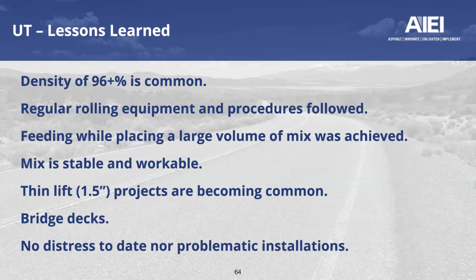What have we learned in the state of Utah? Well, densities have not been a problem almost exclusively. I have density data for 42 projects now. Of those 42 projects, only one has not achieved the target of 96% density, and that particular project achieved 95.7%. And so even the one that didn't meet specs was still a very high density by conventional comparisons.